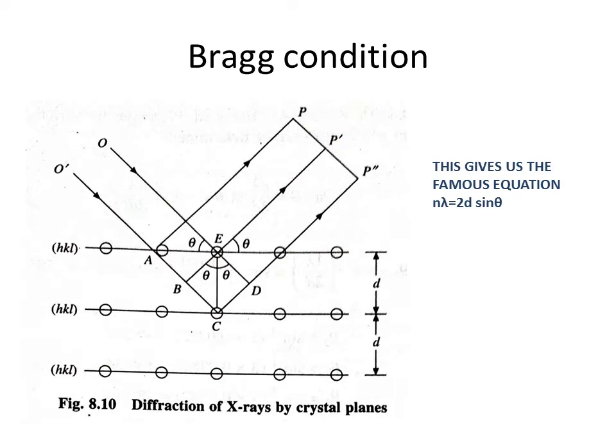Just for the derivation, actually X-ray beams can penetrate deep into the crystal. Even for the normal configuration of the XRD experiment that we do, this angle theta is chosen in such a way that it will be penetrating to a small depth, but in that case also it will be capable of going into the depth of the material in such a way that the diffraction can take place from thousands of consecutive planes. But for this derivation we are thinking about the first two planes.